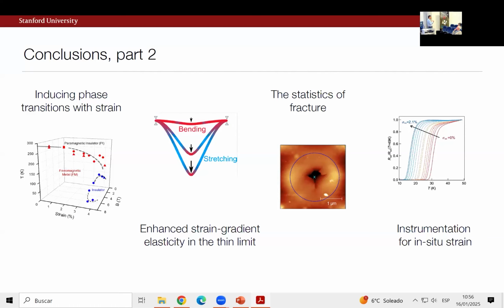Particularly for ionic systems, there can be a dramatic change in the free energy of a defect, right? So let's just take a simple-minded picture. I have sodium chloride or something, right? Then I pull out one of these guys. Generally, these things expand because you have this direct Coulomb interaction. So in that cartoon language, you can imagine, and people have studied, there are dramatic changes in things like defects and so forth. So our struggle before was, if we wanted to go beyond 1% strains, are we really comparing the same thing? Even though we grow with the same conditions, because of these thermodynamic considerations, it's very difficult to do. So you may say then, well, do you not have thermodynamics?